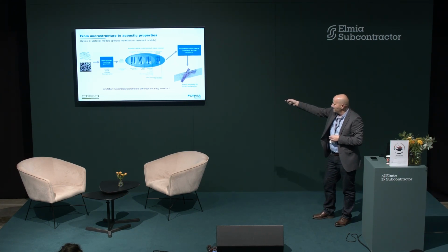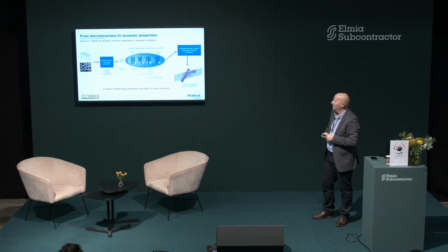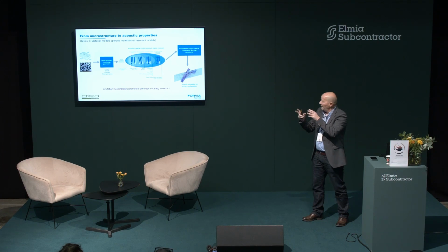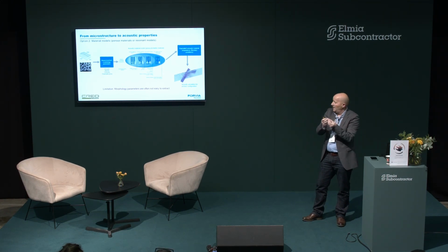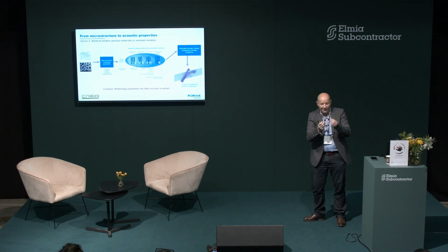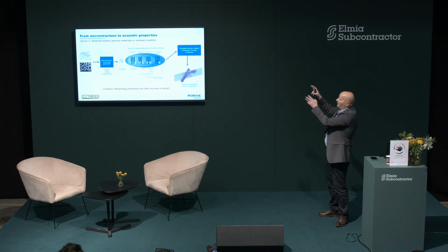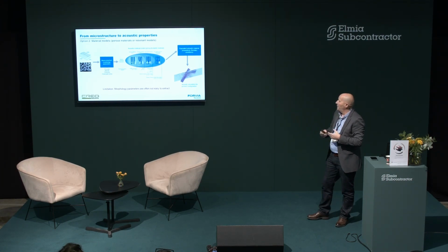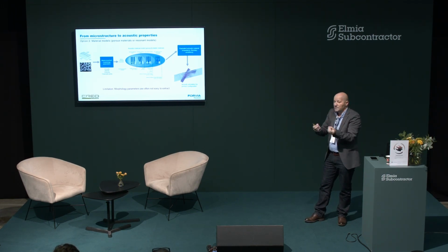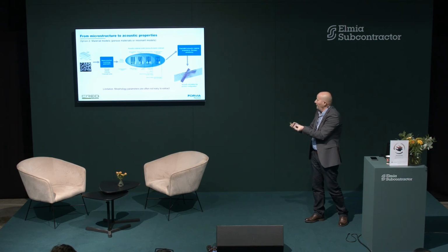a number of models. I will not go into the detail, but what these models are doing is that they are coupling physical information about the morphology, so porosity, density, flow resistance, these kinds of things that are really related to the material, to the final property in terms of parameters that are usable for a simulation.